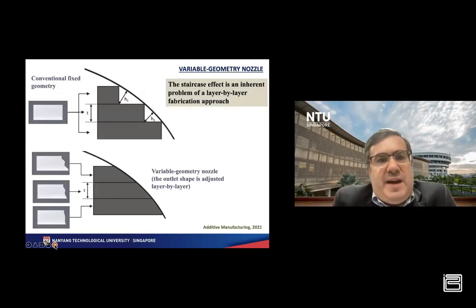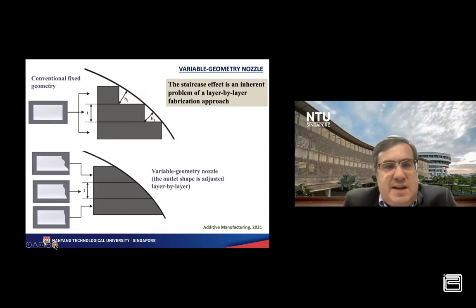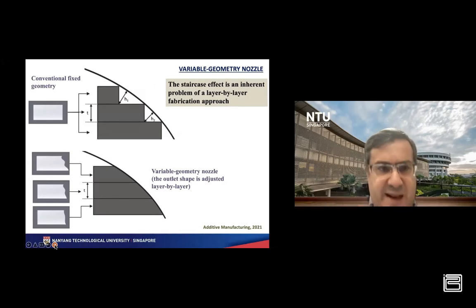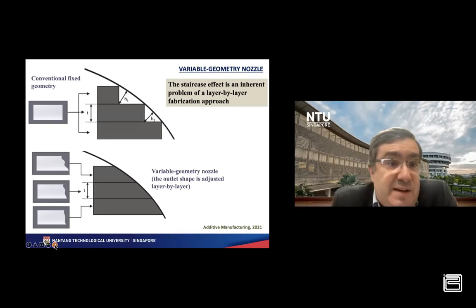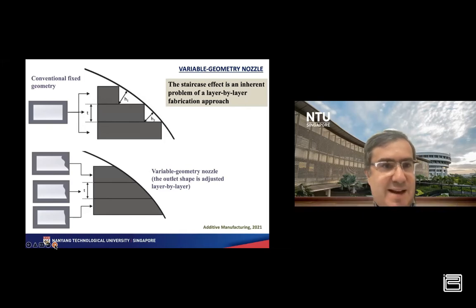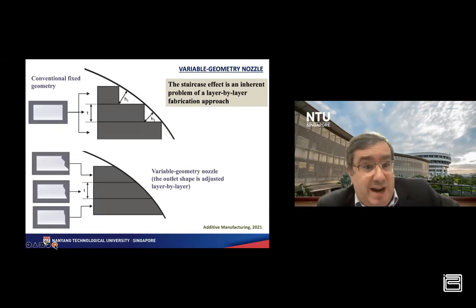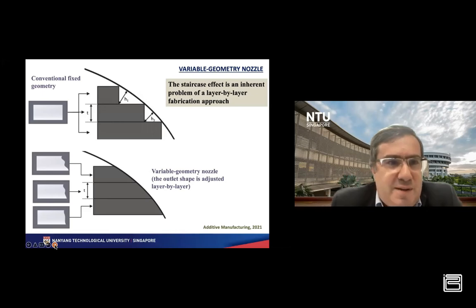Well, another problem that we have in 3D printing is related to the layer by layer fabrication approach. And in the case of curved surfaces, this generates a common problem called the staircase effect. We can minimize this problem by reducing the layer thickness, but this significantly increases the production time. Or another alternative is to use a kind of adaptive slicing approach, which means that we need to deal with layers of different thickness. And this requires a very complex control system because we need to adjust the printing parameters per layer. And in some cases, this is totally impossible. In some technologies, for example, vat photopolymerization, this is totally impossible.